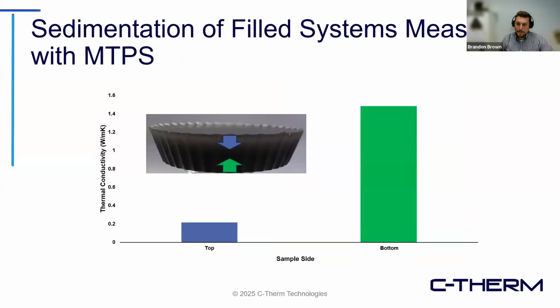Next slide, please. From top to bottom, this is actually a similar problem. Hopefully you can see that there's a slight gradient through this sample. You can see it better on a bright monitor, I suppose, but there's a gradient between top and bottom of this sample. If you were to measure the sample using a steady state method, you would only measure the average through the sample. And this is exactly what happened to a client of ours.